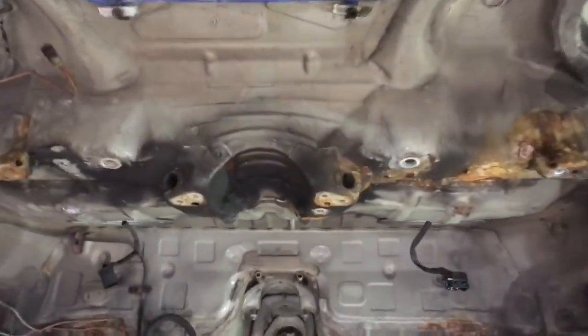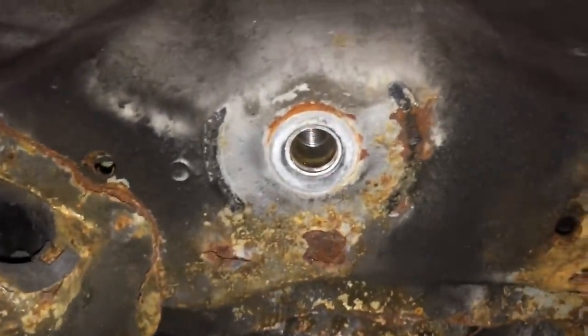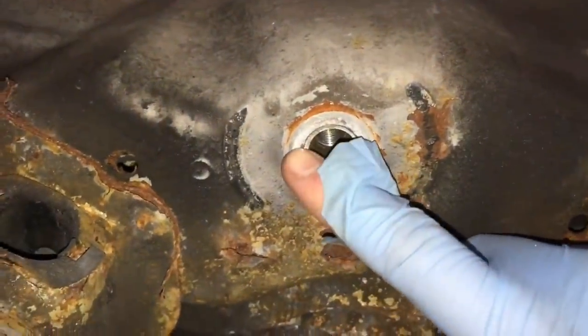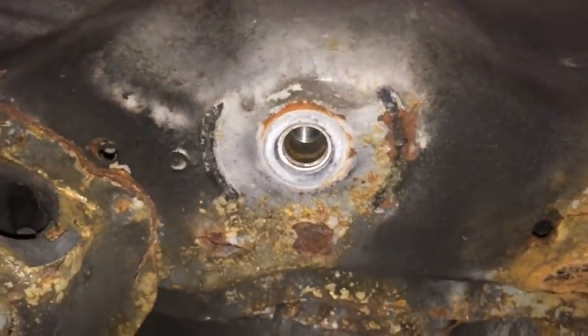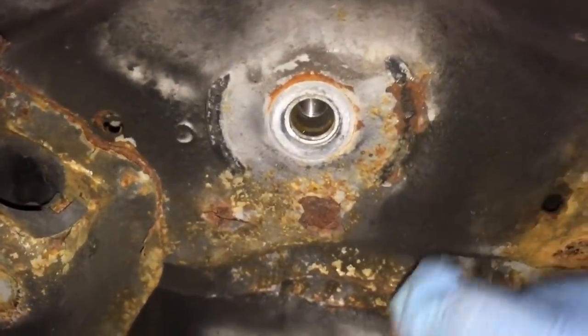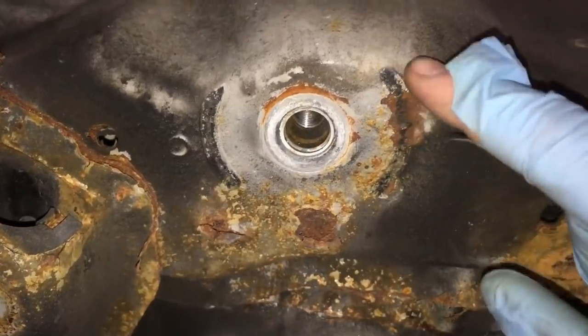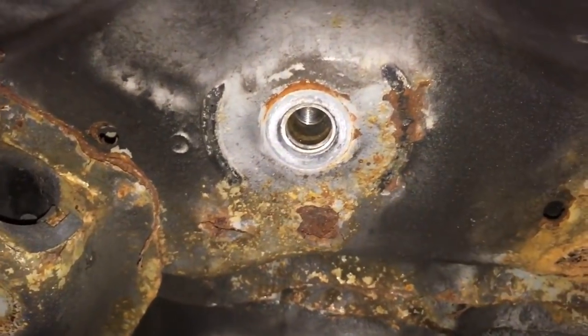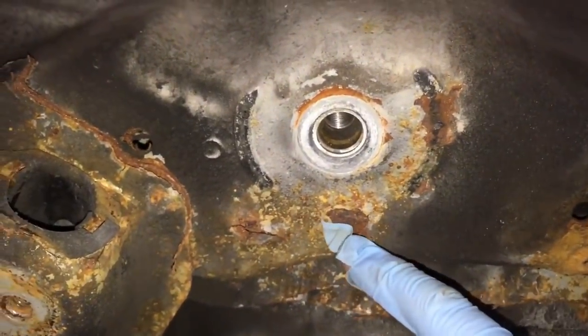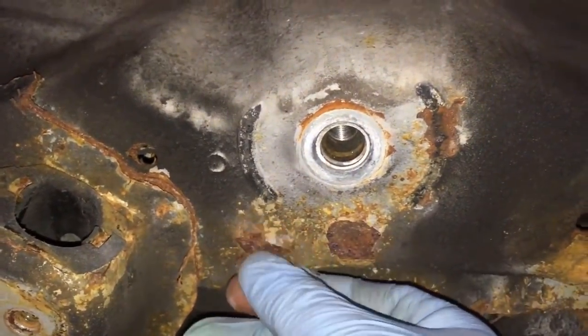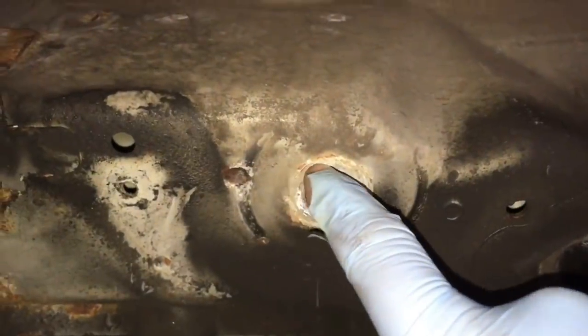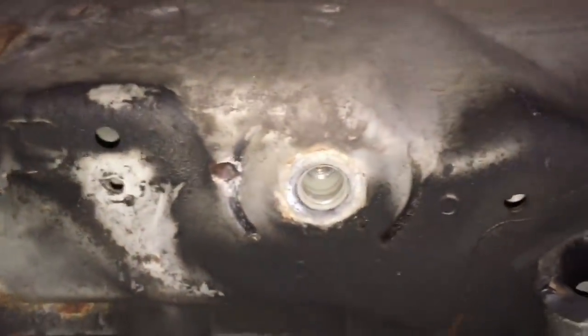Fuel system and the breather pipes are now removed, and we can see before we start degreasing that we've got a semicircle crack going around the mounting point there, a spot weld breakage and possibly a crack where the bush has been imprinting its black markings. Possible spot weld breakage, or certainly a lot of flex on those two, if not. A little bit of crack identification in a corrosion mark around that section.